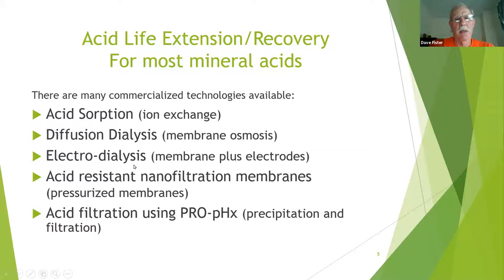Electrodialysis, which is now a membrane plus electrodes. This is a fairly new one, acid resistance nanofilter membranes. So pressurized membranes versus membrane osmosis. Membrane osmosis says the solution or the materials are moving through the membrane because of osmosis. The nanofiltration is you're pushing solution through the membranes with pressure. And then finally, acid filtration using a product called PRO-pHx, which is a combination of precipitation and filtration.